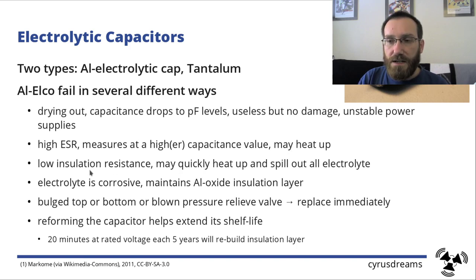and those capacitors might heat up excessively and over time dry out completely, or start to develop low insulation resistance, which quickly heats up the whole capacitor, and that one is the one that spills out all the electrolyte. So you have an internal short that is not self-healing anymore, and that will spill out all the electrolyte on your board. And again, it's corrosive. The job of the electrolyte is to maintain an aluminium oxide insulation layer on the aluminium foil inside the capacitor, so it is able to oxidize aluminium and keep it in an oxidized state. And that will corrode also copper on your board. The traces will then be gone.